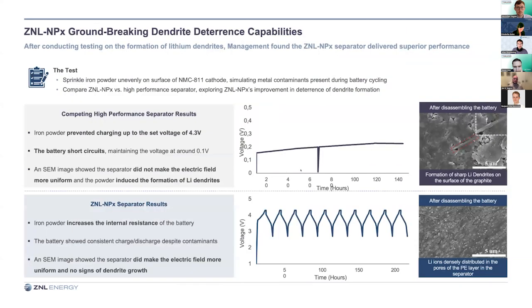We also did an exciting internal test where we put iron powder on the cathode of an NMC 811 cell to simulate what happens during contamination. The conventional separator battery cell couldn't even take a charge. It just short circuited at once. With our separator, it just kept going, no worries, and it went completely fine.